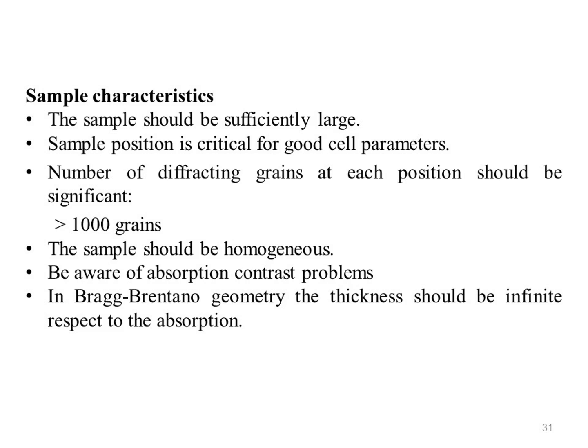Unless a texture analysis is the goal, no preferred orientation should be present. Change sample preparation if necessary. The sample should be homogeneous. Beware of absorption contrast problems. In Bragg-Brentano geometry, the thickness should be infinite with respect to the absorption. Quality of the surface matters.